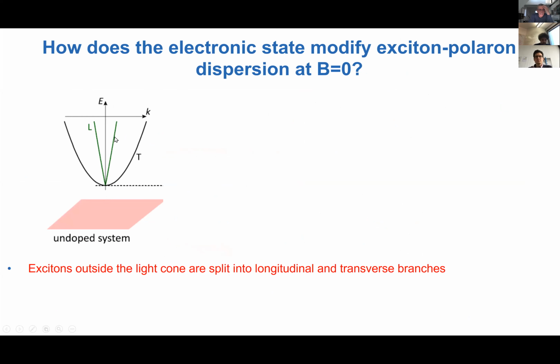Maybe what is not so familiar is that the exciton dispersion, because of the electron-hole exchange interaction, is rather non-trivial outside the light cone. I neglect the light cone here because it exists over a very small momentum. Outside the light cone, there is a large longitudinal-transverse splitting that can be understood as the long-range electron-hole exchange interaction. The splitting scales linearly with momentum because of the longitudinal branch scaling linearly with momentum. And these are normally not observed because the momentum where this is relevant is outside the light cone, and therefore we do not normally have optical probes to see these features.